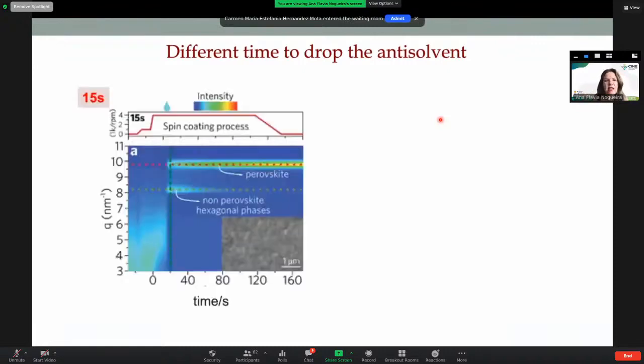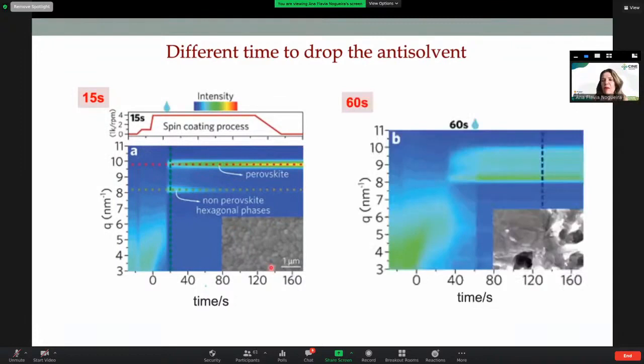Another thing that we studied in this case was the time at which you drop the solvent, because it was done manually by my postdoc. You can see here, this is the data that I showed you before. We dropped the solvent 15 seconds after starting the spin coating, and we end up with a very nice morphology. But look what happened. If you take much more time to drop the solvent, the morphology is really, really bad.